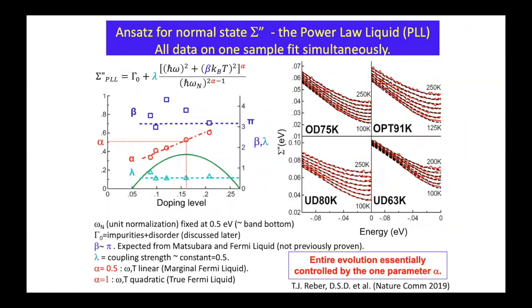Lambda, this coupling thing, says it's linear in T or something near that. Well, how fast does it go linear in T? That's my coupling parameter, lambda. I find that's essentially doping independent at 0.5. And this is basically this Planckian dissipation, but more details on it. This is a very pleasant surprise, that this is so constant. And then everything else just comes linear. The key thing then is alpha. That's the thing that's varying. I already showed you that it goes to 0.5. If you extrapolate to much higher dopings, eventually, imagine this might come to 1, and that would be a Fermi liquid, quadratic in omega, quadratic in T, scattering.